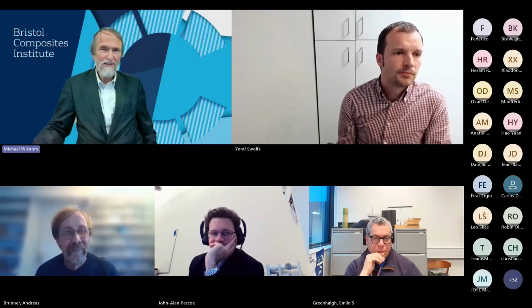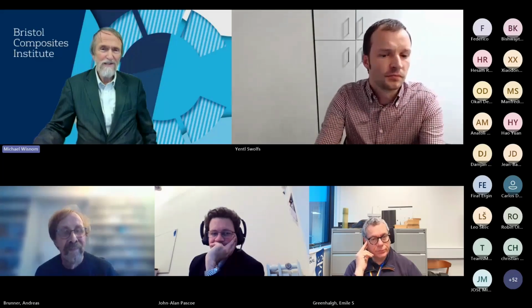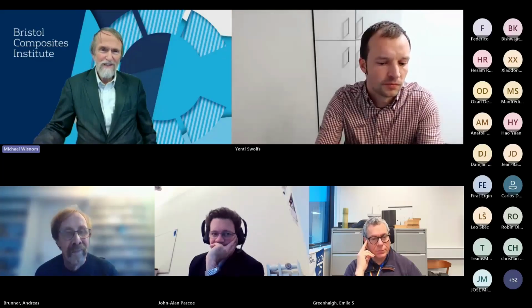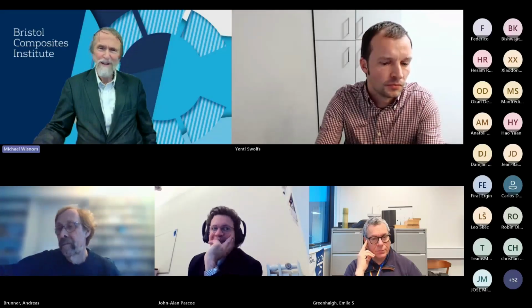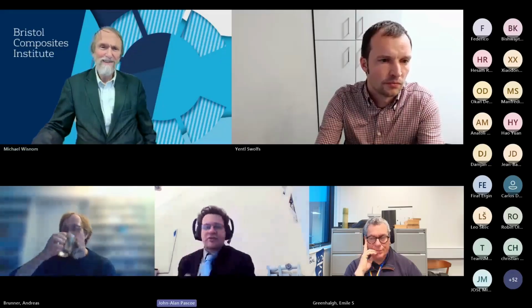Go ahead, Michael. Yeah, so you showed a picture where you were talking about delamination to the 0, 0 interface, and you're showing mode 2 and mode 3 contributions. But I mean, you don't usually get delamination at a 0, 0 interface at all. And if you did, surely it couldn't be mode 3 because it would migrate, wouldn't it? Yeah, exactly. So that's exactly what happens. So the delamination location is artificial because you put a Teflon insert at the midplane. And so we have a 0, 0 midplane with an artificial insert in there.